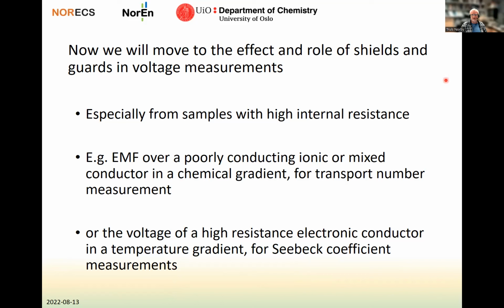Now we will move to the effect and role of shields and guards in voltage measurements. Especially because what you have seen now is that in impedance measurements, it works quite fine with these shields to reduce noise. Now we will see that in voltage measurements, it comes out a bit differently. This is especially relevant and important for samples with high internal resistance. For instance, to measure the EMF over a poorly conducting ionic or mixed conductor in a chemical gradient to measure the transport number. Or to measure the voltage of a high resistance electronic conductor in a temperature gradient to get the Seebeck coefficient.